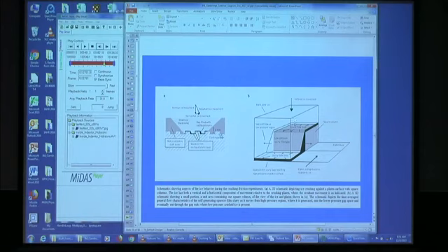That gap fills in with the slurry that's flowing from the horizontal flat surfaces, and so it creates a back pressure. It's a pressurized slurry. By definition, the friction on this rough surface is determined by the difference in force on the front side and the back side of that prominence. So when it fills in with slurry that's pressurized, you have a balancing act. As long as you're doing some crushing, you end up with very low friction coefficients, even though it's a very rough surface. That has a lot of implications, I think, for many different applications.